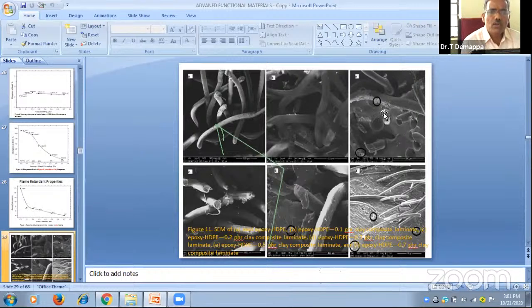This is 0.2 phr, where the mechanical property increases because the dispersion is good, with good interaction between the epoxy and the clay. The interfacial adhesion or interfacial bond is very high in this region. After 0.3 phr, agglomeration takes place and cracks develop. Okay, you see these are the cracks, you see these are the cracks and agglomerates. That's why the mechanical property decreases and other properties also decrease.